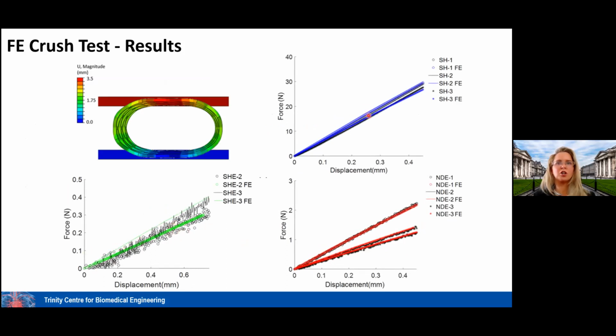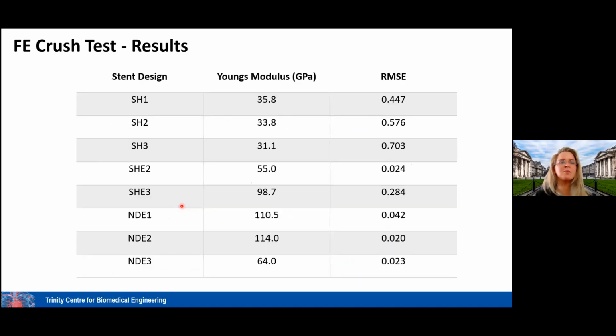So these colored curves here are showing you what is the Young's modulus calculated to be when we match those experimental curves from those 9 different stents. If we replicate them in the finite element model, what Young's modulus is needed in order to get that same deformation seen experimentally. And here is a table of that. So for the 3 different simple honeycomb, the 2 simple honeycomb etched, because one had a fracture, and then the 3 novel design etched, we were able to calculate what would be the Young's modulus needed to create that deformation